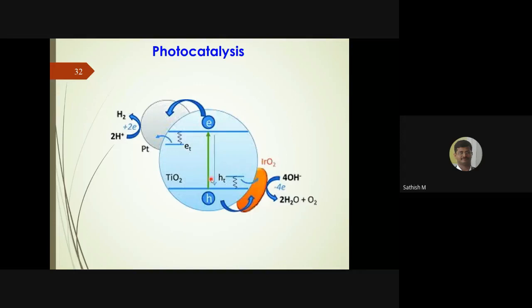The more important thing here is the energy which you are giving to the system. For example, if the light energy is not sufficient to excite an electron from here to there, then the light may not be absorbed by this system. The absorption of light mainly depends on the band gap of the particular material. For example, TiO2 is one of the best known photocatalysts for hydrogen production or even for decomposition of pollutants. But unfortunately, the band gap of titanium dioxide is 3.2 electron volt. Converting 3.2 electron volt into wavelength gives almost 382 nanometer. So to excite an electron from the valence band of TiO2 to the conduction band, you should shine light with a wavelength of 382 nanometer or lower. Only then can you excite one electron.